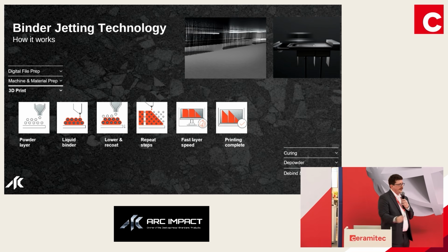And when we do that, we put down a powder layer. We add liquid binder in a predetermined specification where to drop it. We lower that down. We put more powder. We repeat until we've built up all of our layers, and we have our finished print. That is then taken out of the machine, sent off to curing. Once it's cured, we depowder. Once it's depowdered, we put it in for our post-processing. Usually a debind and sinter, but there's multiple techniques available for your post-processing.